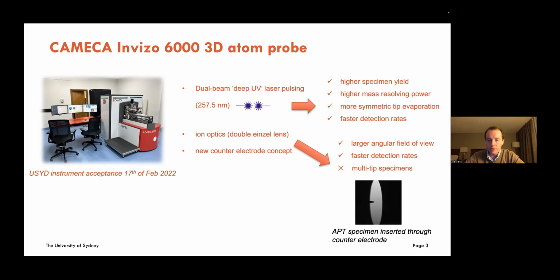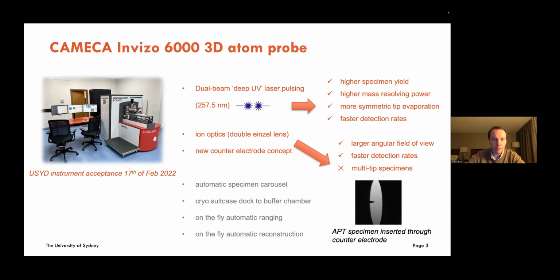But we can't run multi-tip specimens with this new configuration, so you have to actually insert your atom probe specimen through the orifice of the counter electrode. Because of that, we need to change up a few of the protocols around particularly FIB-based specimen preparation. We can't look at multi-tip arrays and grid-type specimens.